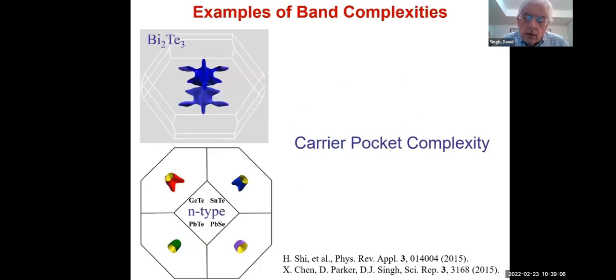So a key point in lead telluride was the fact that the electronic structure was unusual. In other words, the band structure was not a parabolic band structure. And often that's the case in thermoelectrics, that you're looking for things like that. And you would seek materials that have high ZT, but you would understand that the isotropic parabolic band, single parabolic band, may not be the optimum band structure for that. And you may be looking for other kinds of band structures, and you'd like to be able to compare different materials in order to make predictions of materials that experimentalists might like to investigate.